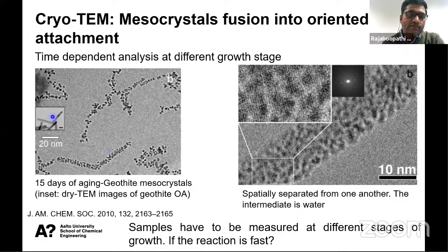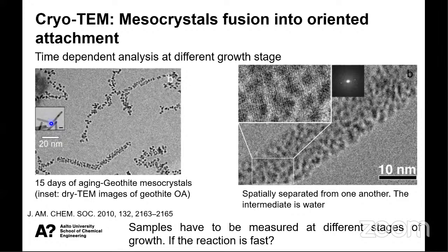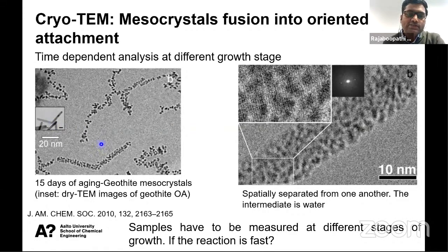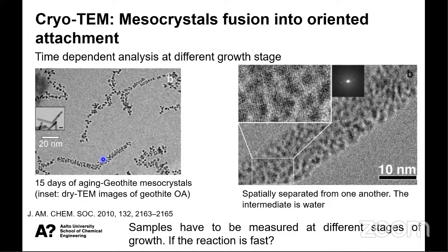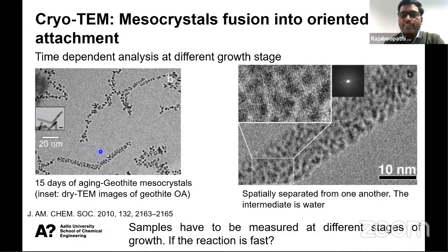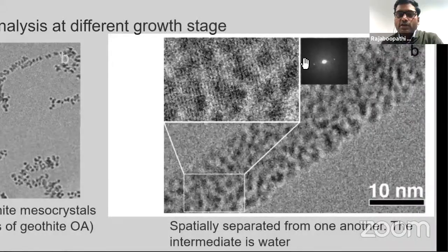So this is the oriented attachment of iron oxide. This is mesocrystals of iron oxide, where you can see the attachment of particles. So if you keep the solution for a particular time, for example, in this case, they kept the solution for 15 days to get an oriented attachment, where you can clearly see the particle attachment, this is the mesocrystals.